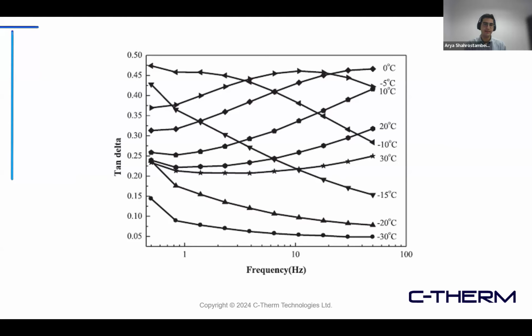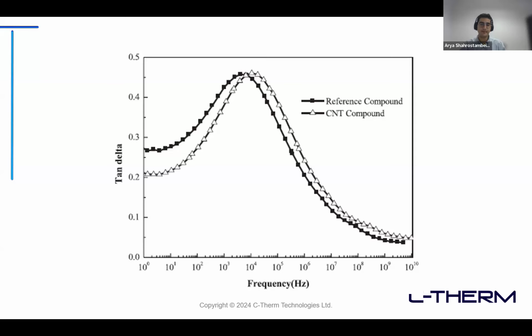Basically, the way that they use WLF or master curves is that you start running your test over a range of frequencies. For this test it is 0.01 hertz to almost 100 hertz at different temperatures, starting from -30 all the way up to 30 degrees C. Based on different temperature and different frequency, you see different behaviors of your material. And based on the WLF model, you'll be able to interpret that data and calculate the behavior of your material at very high frequencies that is actually impossible to measure experimentally. For example, the frequency that has been calculated here is 10 to the power 10 hertz, which is impossible to measure experimentally with the current technology available. So that's a very nice option for us to understand the behavior of material at higher frequencies.